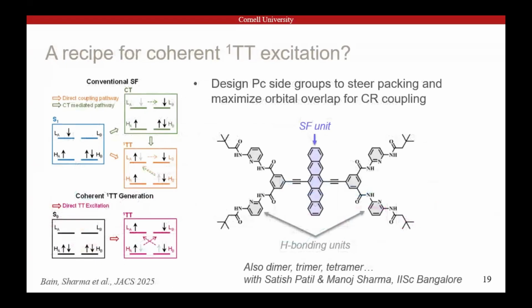So we sat down with our synthetic collaborator and we thought, is there some way that we can really ramp up this effect? And the very crude idea from the spectroscopy side was, why don't we just crank up the charge resonance coupling as much as possible? For us, that means smoosh the molecules together so the orbitals overlap more. So we had this idea: let's pin the pentacenes together with these very strong hydrogen bonding units, hold them really tight, and see what happens. See if we can ramp up this orbital overlap and change the photophysics.